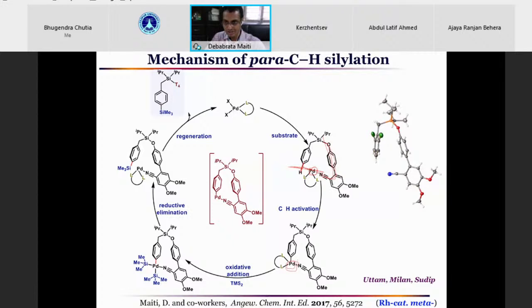This is the crystal structure of the substrate, which clearly shows that the metal will be positioned here and will activate the CH bond just preferably here. Okay, the ortho as well as meta-CH bond doesn't get activated. Okay, and very recently we were able to show that rhodium can be active at the meta as well as para position. I think I'm coming very close to my time.